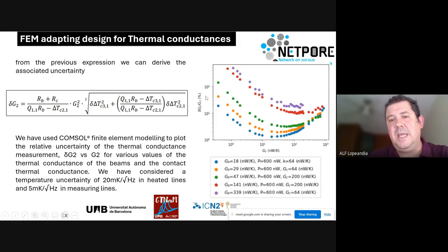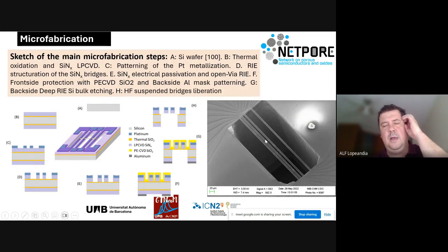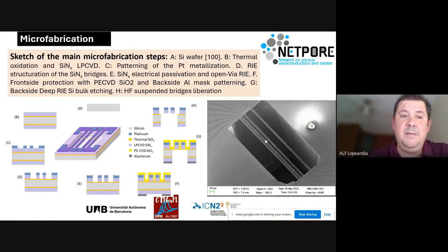And this is just taking into account the uncertainty, if we are able to determine the temperature in the heated line with 20 millikelvin per square root of Hertz during the measurement, and with a measurement of 1 second, and consider that we are able to determine the temperature of the measuring lines with bridges and differential measurements of 5 millikelvin. Then, taking that into account, we did a modeling, we did a design, and we fabricated that design. Just consider that this is the fabrication procedure.